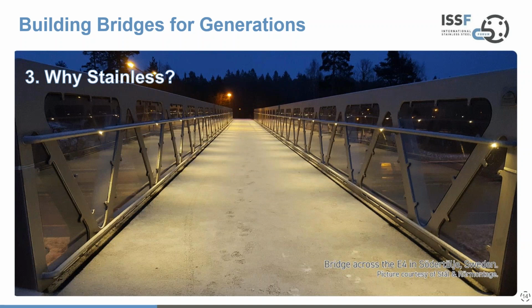Now, it's an interesting question, which I think is best answered by thinking about what can happen in a freeze-thaw cycle, particularly if, to encourage the thawing of snow or ice on bridges, de-icing salts are used. And that in itself can create a problem, not so much for the right stainless steels, but certainly for carbon steels. But really it depends how low in temperature you're going to go.